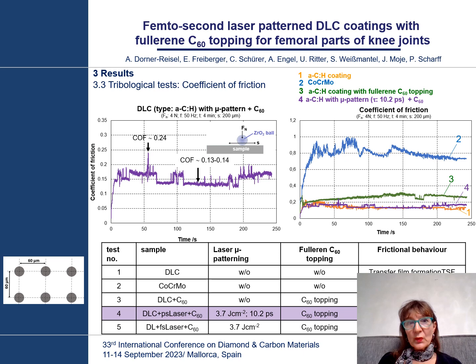The orange curve belongs to diamond-like carbon without micro-patterning, without C60 topping. The lilac curve belongs to DLC with picosecond laser patterning and C60 topping. We can see that it is almost the same level, like DLC without patterning and without C60. It is just a little bit more irregular.